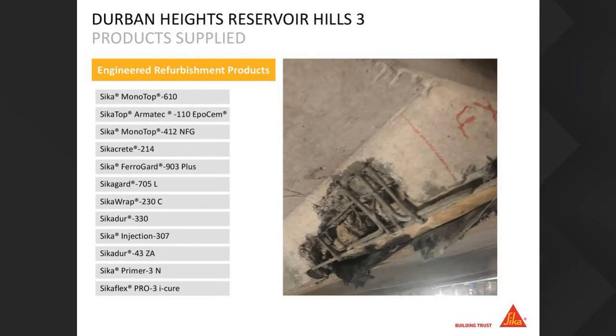I just want to touch on maybe one or two other products that I haven't mentioned in this presentation. The Sika 43ZA epoxy mortar that we used to repair around the injection ports. We needed a very strong bond because we went up to, at some stage, I think, up to 12 bar of pressure. So we needed a strong bond between the repair material and the concrete itself. We also applied 26,000 square meters of Sika Ferrogard 903 Plus. That was spray applied. The Sika Ferrogard 903 is a corrosion inhibitor.